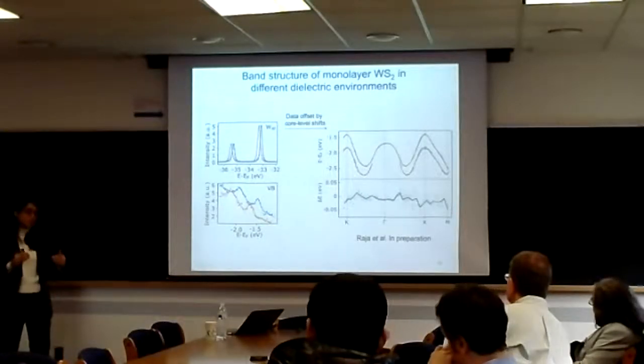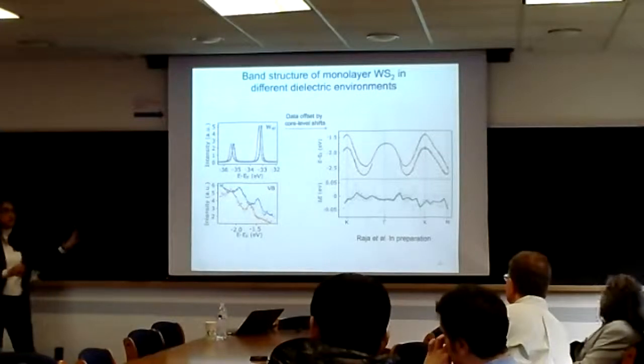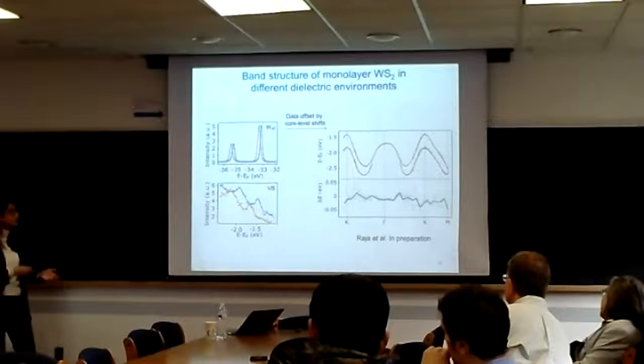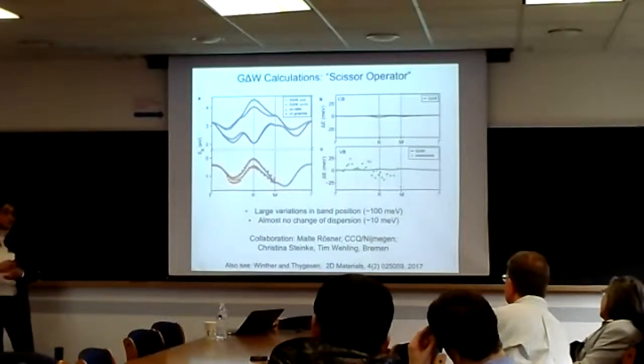And we also have to do the perfect calibration for the band alignment. You need the secondary electron emission, which is not here. So what I can tell you right now is that it's a rigid shift, and you're not really changing your band structure, and it is in a way non-invasive.